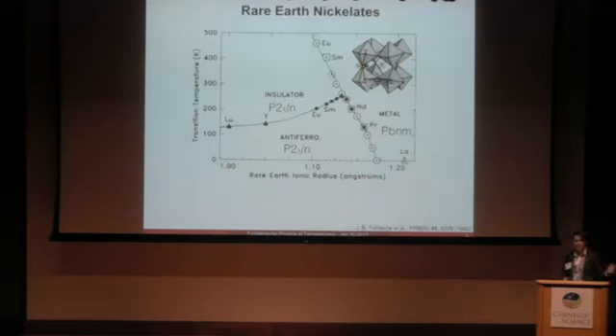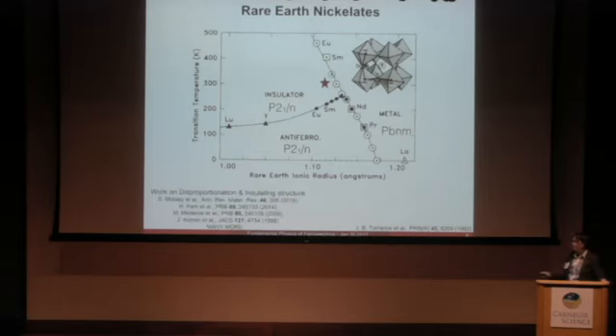So some of you might be familiar with the family of rare earth nickelates. They have a very well-known metal insulator transition that occurs for all of them except for lanthanum nickelate. Going through this transition, the structure changes from PBNM to P21/N. At room temperature, which we have mostly studied this material, samarium nickelate is an insulator, but it doesn't show a large charge disproportionation. So this topic of charge disproportionation and the insulating structure is very well studied, maybe not very well agreed upon, but that's not what I'm going to be focusing on in this talk.